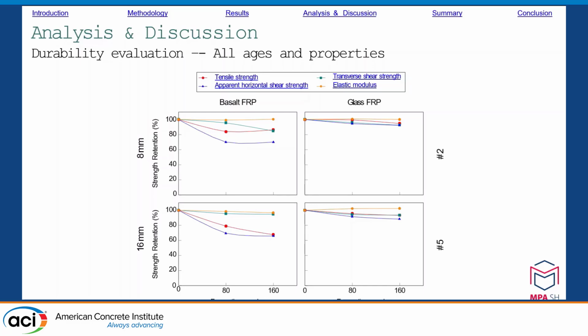The green line summarizes the results of the transverse shear strength tests. A drop in the retention capacity between 80% and 95% can be seen here. The blue line shows a significant loss in the retention capacity of the FRP bars. This shows the horizontal shear strength, which drops significantly to approximately 65%, especially for the basalt fiber rods. The retention capacity of the tensile strength is roughly between that of the transverse shear strength and the horizontal shear strength. Overall, it can be seen that the glass fiber rods have a higher retention capacity in all tests compared to the basalt fiber rods.